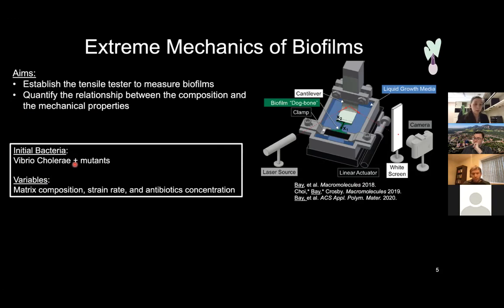But the reason why we would do these is because, one, they're well quantified in terms of the rheology already, in terms of the gene knockout. So it's just a nice initial protocol to check that we are getting similar responses to the rheology, and are we seeing different responses in terms of the cohesion? And then, because these are viscoelastic in nature, can we look at the strain rate effects and potentially put these into a dynamic mechanical analyzer and do DMA and see if we can see these viscoelastic effects.